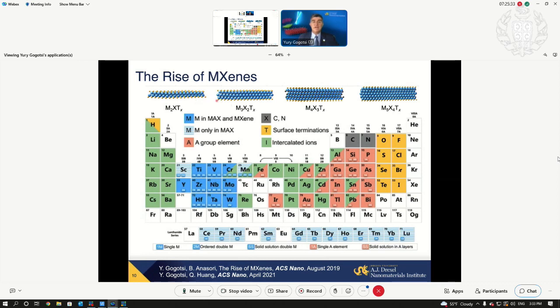But they also have surfaces terminated by oxygen, OH, chalcogens, halogens, at least 10 different terminations. If you do the math, taking into account the 2, 3, 4, or 5 layers of transition metal, which we call M element, X stands for carbon and nitrogen. This is where the name MXenes comes from. T stands for termination. There are at least about 1,000 simple compositions possible.